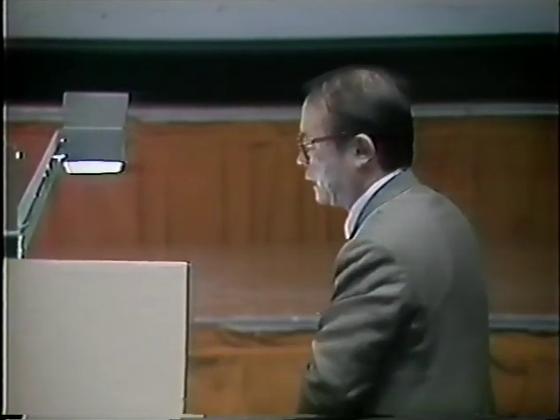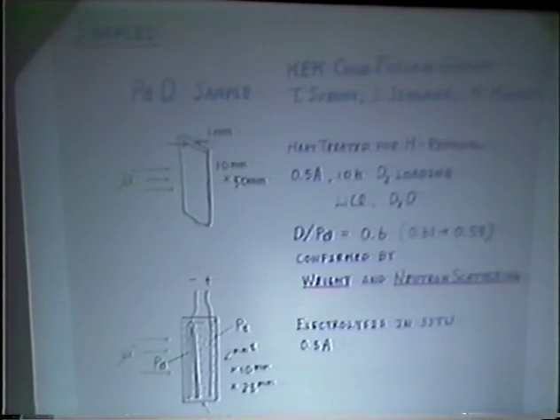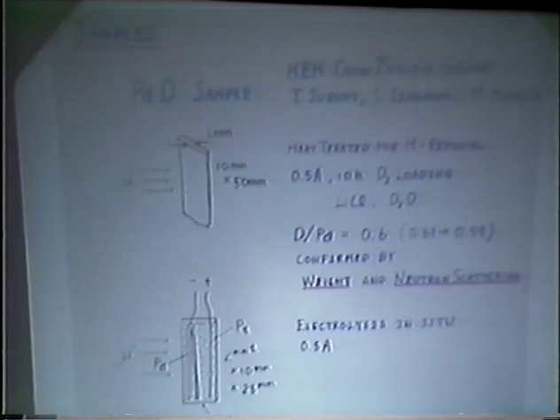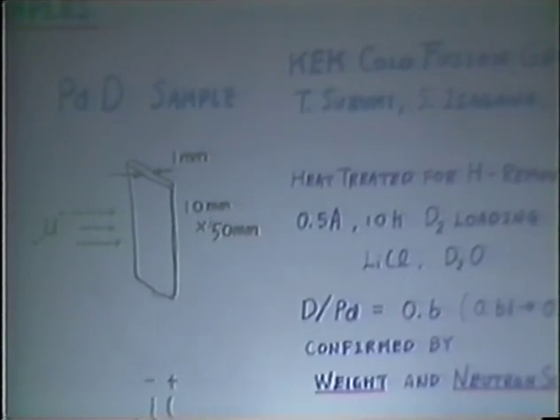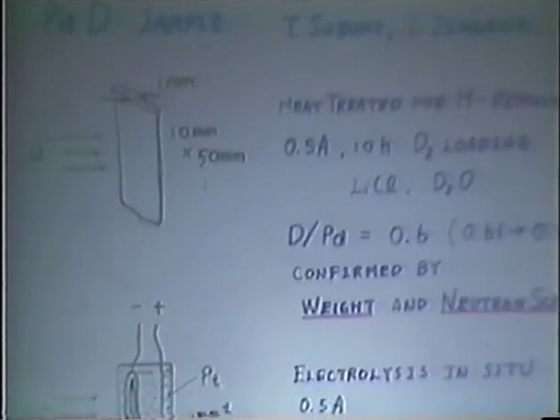The samples we adopted were mainly prepared by the KEK cold fusion group, and are summarized here. The palladium deuterium sample has this size, and we loaded deuterium for 10 hours up to a D per palladium ratio of 0.6. This deuterium concentration was confirmed by not only weight measurement but also neutron scattering.